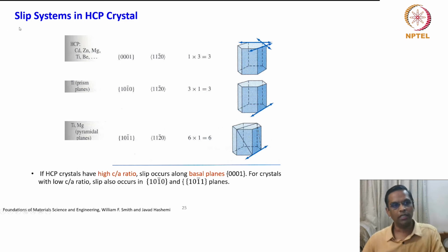Similarly, if you look at the slip systems in hexagonal close packed crystal, the primary slip systems are the basal plane. You can see that this is a basal plane, and the directions are given here: 3 directions, 0001 basal plane and 112bar0 with 3 directions. So 1 into 3, 3. Examples of this kind of slip system exist in cadmium, zinc, magnesium, titanium, beryllium.